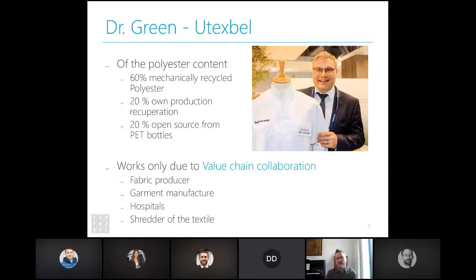This is only possible because those garments have a huge number of washing cycles. So after 100, 120 washing cycles, the cotton is completely dead and will pulverize during the recycling and spinning. So that's why you end up with these polyester fibers. From the moment you try to recycle better garments or other garments, probably you will have issues. So it's very important that you have a value chain collaboration. And this is often the case, that you need everybody within the value chain to work together.